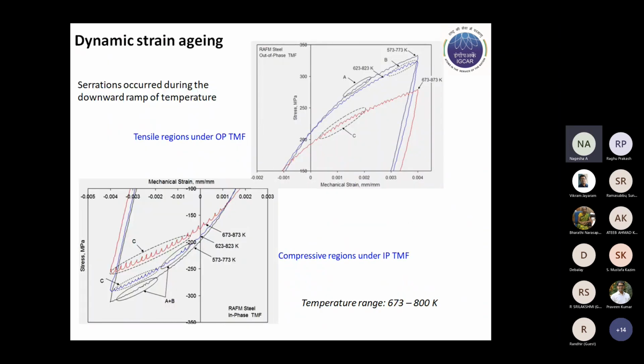There is another important result I would like to show, which is the occurrence of serrations in this loop, in the OP TMF. This alloy is prone to dynamic strain aging in the temperature range of about 400 to 500 degrees centigrade. In OP TMF this happens on the peak tensile side, where the tensile direction is colder. So the serrations were seen largely in the tensile part under OP TMF, and depending on the temperature traversed during the testing, the nature of the serrations also changes.